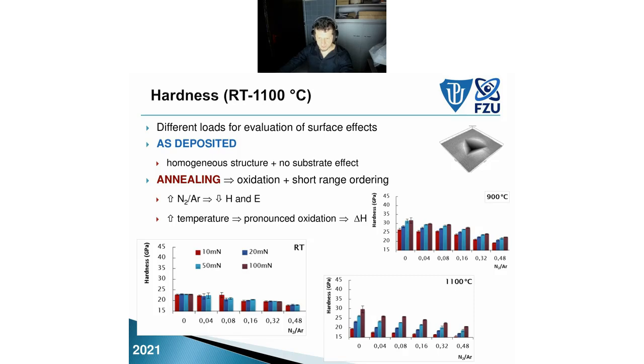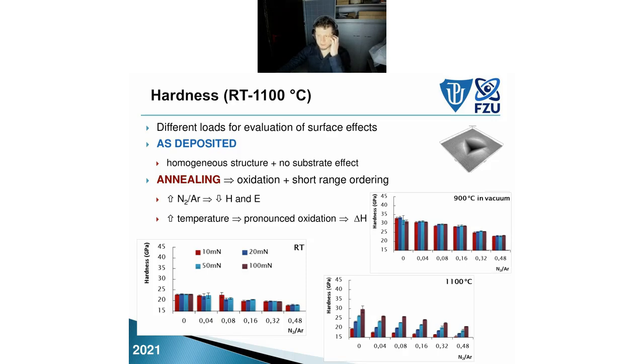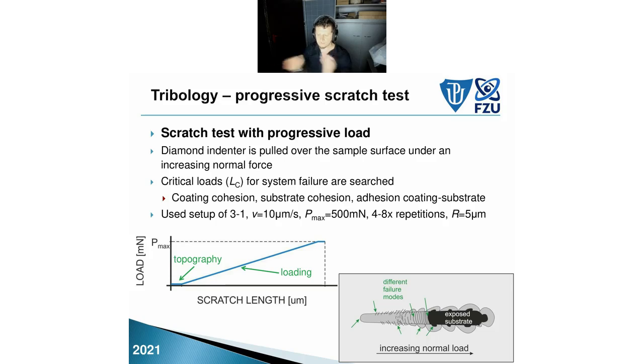to oxidation. This oxidation effect we have tested using vacuum indentation, because during the vacuum indentation at 900 there is no oxidation layer, so we also see there is no depth effect during this indentation, and we just see the increase of mechanical properties. But let's check the tribological tests.